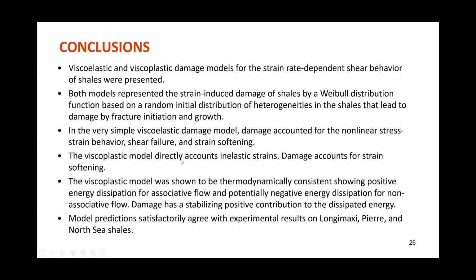The viscoplastic model accounts for inelastic strain, unlike the viscoelastic model. And again, damage accounts for strain softening. The viscoplastic model was shown to be thermodynamically consistent, showing positive energy dissipation for associative flow and potentially negative energy dissipation for a non-associative flow, like all constitutive models out there with a non-associative flow rule. However, damage has a stabilizing effect and opposes the negative work that is done by the plastic deformation for non-associated flow.